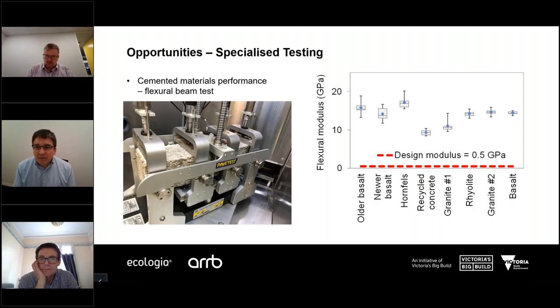Often in Victoria, a cemented subbase is designed as a working platform with a 500 MPa modulus, or a 0.5 gigapascal modulus that's shown in the red dashed line. And the chart shows the results for a recycled crushed concrete aggregate in the middle, which is about less than 10,000 MPa, 10 gigapascals, and how it relates relative to a range of other virgin materials. And you can see they're right up there in terms of flexural modulus, and certainly well exceed a design modulus of 0.5 gigapascals. So quite applicable to use, and hence we can see the good performance as I showed earlier on the Western Ring Road over many decades. Next slide, thanks.